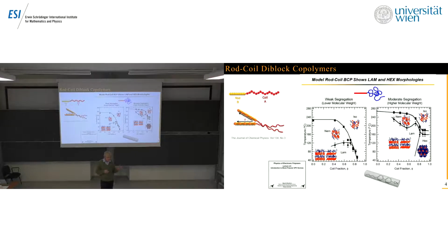So this microphase separation, and the fact that the two parts of the macromolecule are linked together, creates an instability at a certain wave vector, and as a result there is a periodic structure: simple lamella, more complicated hexagonal, or even more complicated cubic ones with several density waves. And in addition, if we have rods, then of course rods interact. There is a liquid crystal type interaction between rods, and this brings also all types of liquid crystal effects, like the tendency towards smectic ordering. The longer the rods in conventional liquid crystals, the stronger the tendency to form smectic phases.